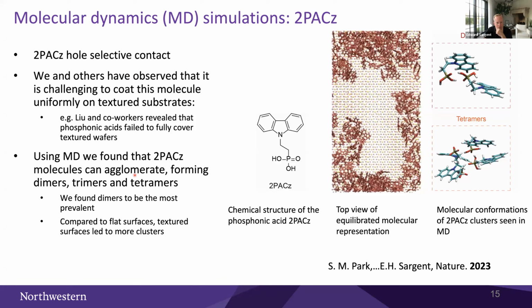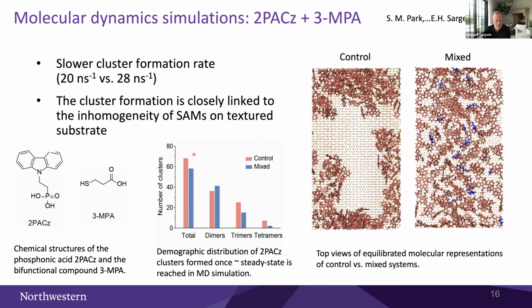And we found evidence initially using molecular dynamics that one of the things that can happen is that these passivation molecules can actually agglomerate. They can make dimers, trimers, and tetramers. We saw mostly dimers, but a few of the higher order ones as well. And our idea was that this could potentially lead to local clusters rather than the desired uniform coating.